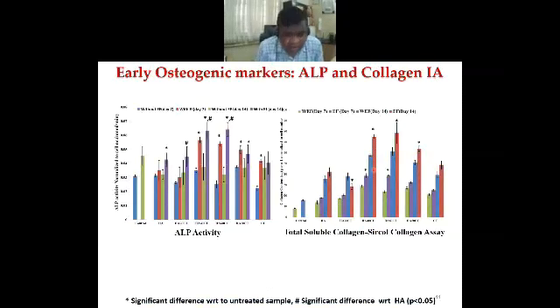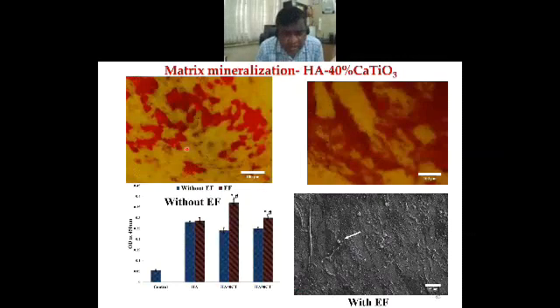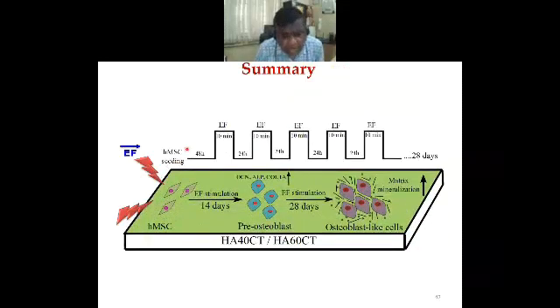Now, ALP activity and collagen content are the markers for osteogenesis. Again, around 40% calcium titanate addition, both ALP activity and collagen are significantly modulated compared to non-treated surfaces or hydroxyapatite alone. So this has been marked here. Our overall understanding is that when you give this electric field stimulation, after 14 days we have found osteocalcin, alkaline phosphatase, and collagen type 1A upregulated. After 28 days, we have found that matrix mineralization is enhanced, and then essentially it is leading to more osteoblast-like cells.